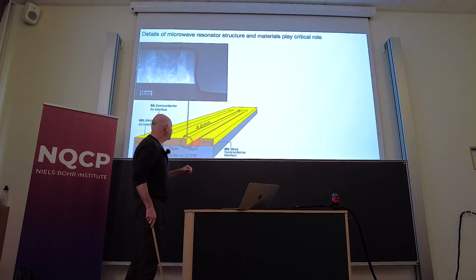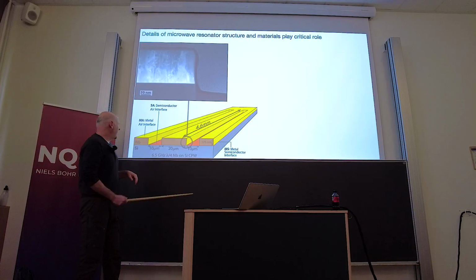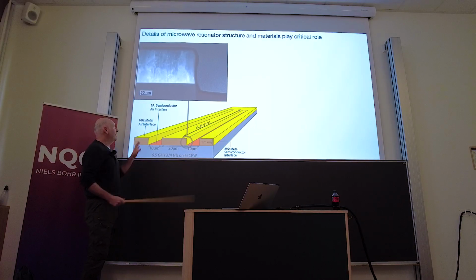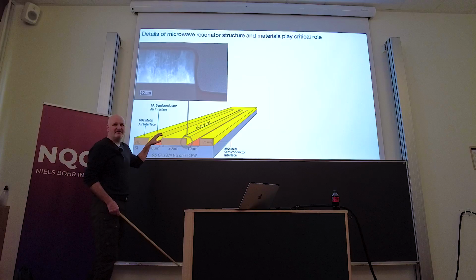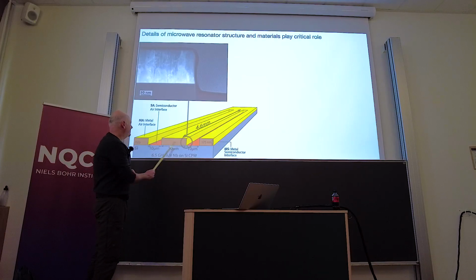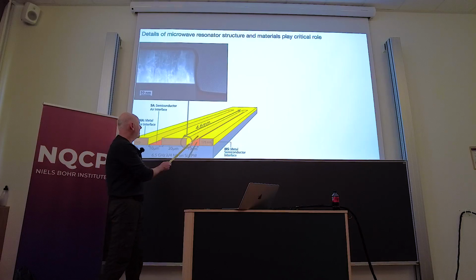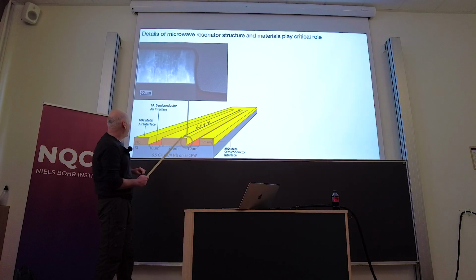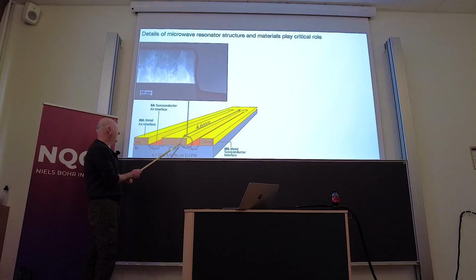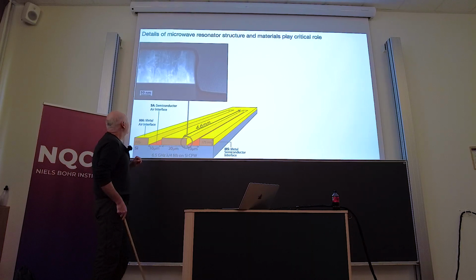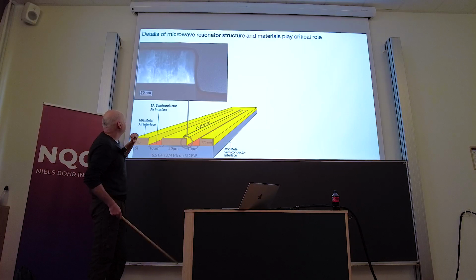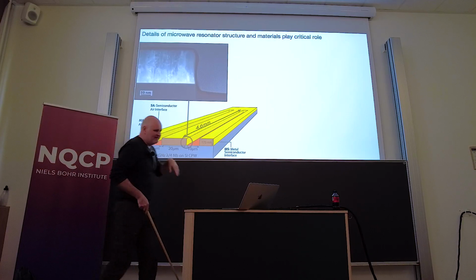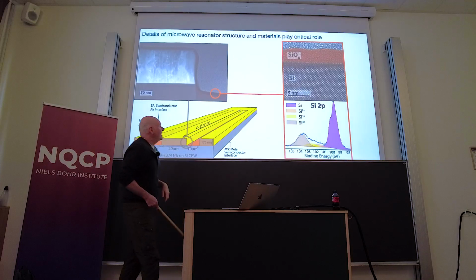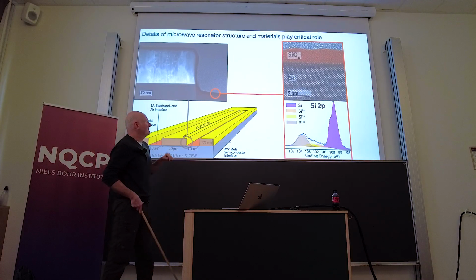So if you look in cross-section of these waveguides, everything we're doing here is niobium resonators on silicon. So you have your silicon substrate. You have these very long wires, essentially, of niobium. And you have two interfaces, essentially. You have the interface between the silicon and the niobium, and the air or vacuum or whatever. And so we took cross-sections of these, and what you see is, of course, non-ideal interfaces.